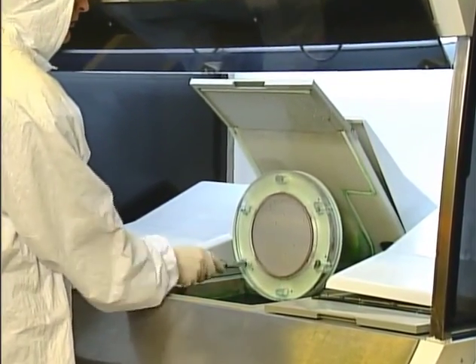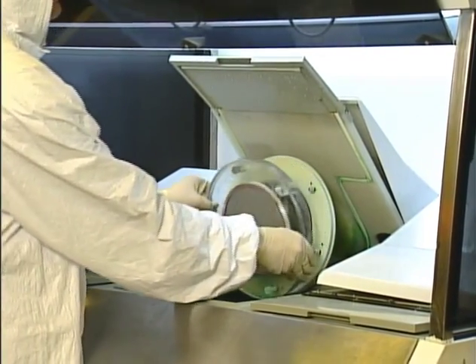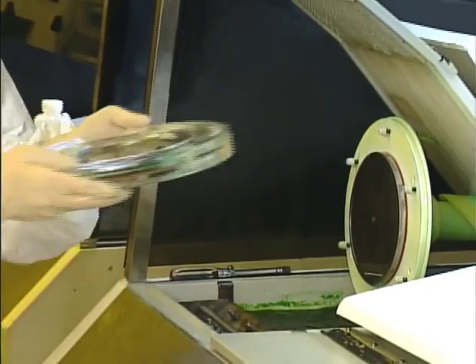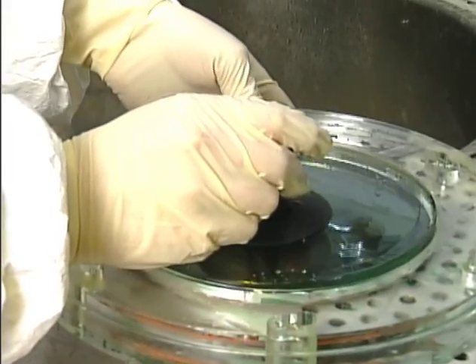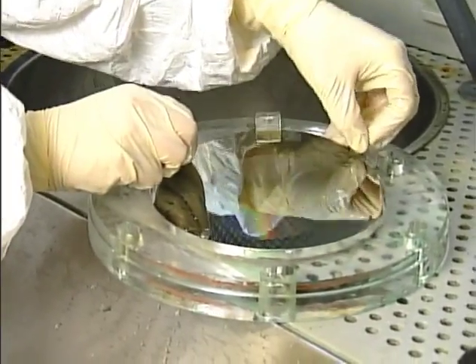A metal stamper, which is a negative image of the master, is formed by electroplating a thicker layer of nickel onto the existing layer. The resultant nickel plate, called a father, is then peeled off, allowing the glass plate to be cleaned and reused in the mastering process. The father stamper is used to form a positive image known as a mother. The mother can produce additional sons identical to the father.